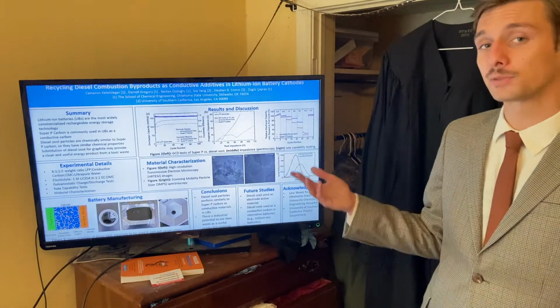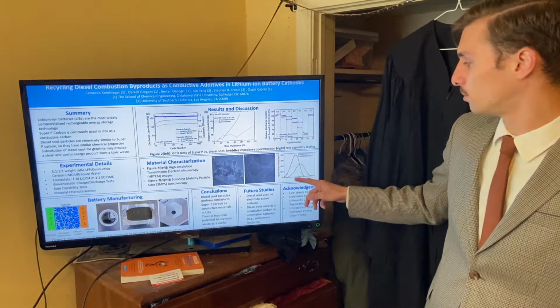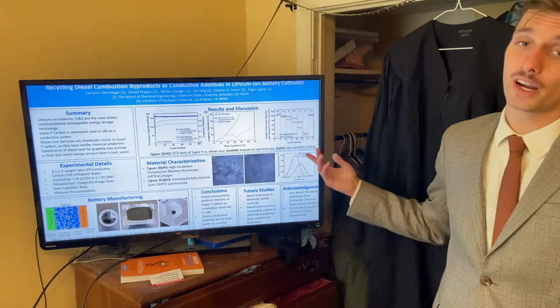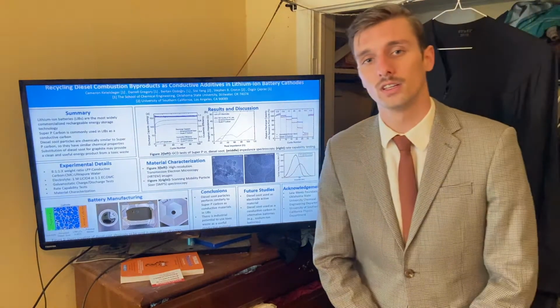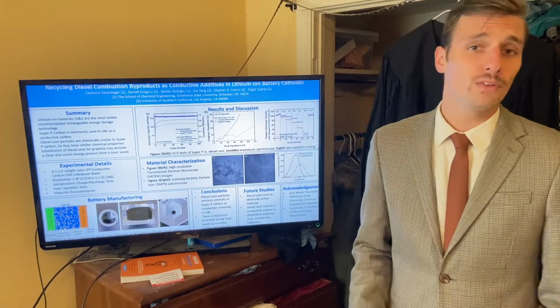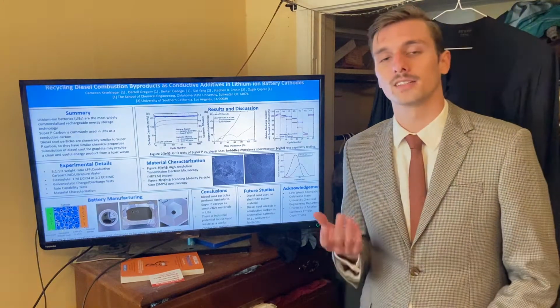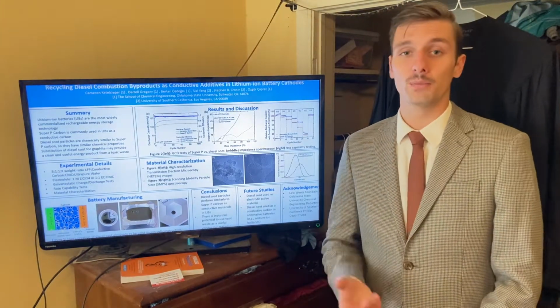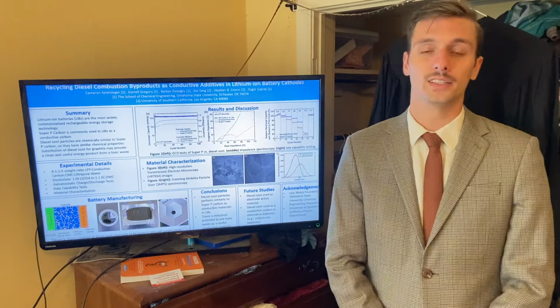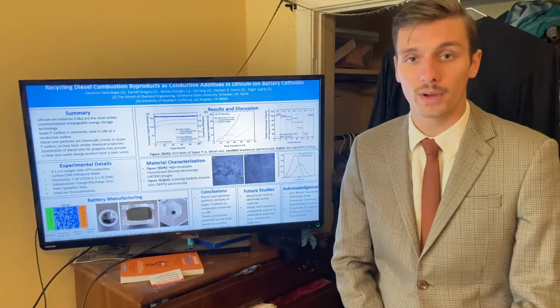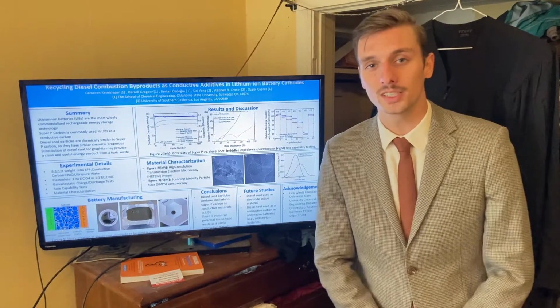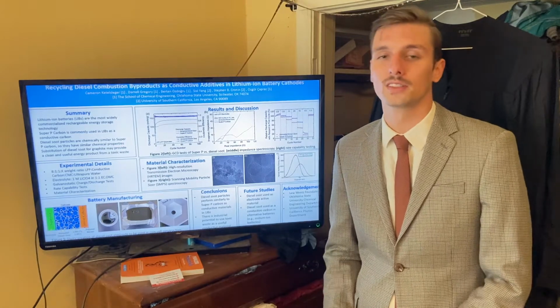However, we found average particle sizes for low engine load to be about 50 nanometers, and for high engine load about 100 nanometers. Regardless, what we found through this study was that diesel soot is a viable alternative to Super P as a conductive carbon additive in lithium-ion batteries, and that there's industrial potential to use this waste as a useful battery component.